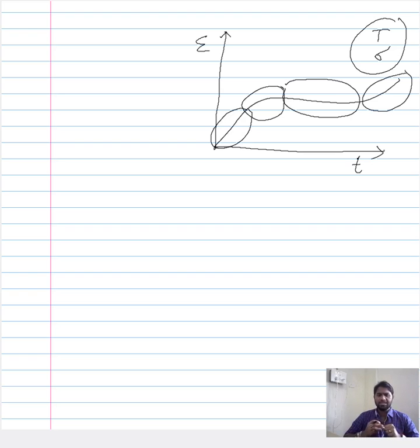And moreover, since the instantaneous creep is so much quicker when you compare it to the overall duration of the creep test, it can be ignored, and then stage 1 would comprise just the transient creep. We also saw that when you take the purely engineering view, according to Professor Dieter, your creep curve would comprise 4 stages, and these 4 stages would involve instantaneous creep, transient creep, steady state creep, and the tertiary creep.